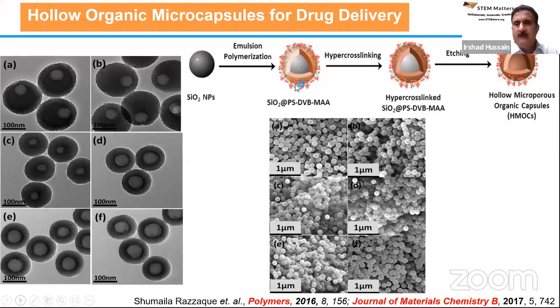We also designed and developed these kind of microporous organic polymers which were hollow in nature. In this case, we initially used silica nanoparticles as sacrificial templates and then grew these porous polymers around them by emulsion polymerization. And finally, you can remove the silica nanoparticles by etching and produce these hollow polymer nanoparticles, which are microporous in nature. Then you can functionalize these with different anti-cancer drugs to improve the bioavailability and pharmacokinetics of these kinds of drugs.